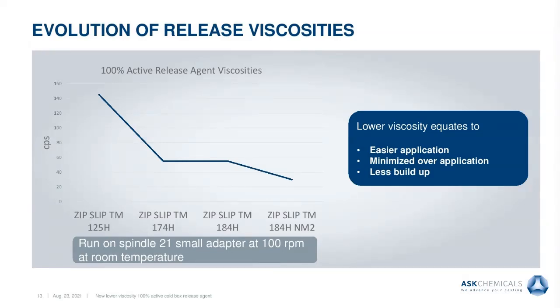100% active release agents have existed in the foundry market for decades. Viscosity is checked using a Brookfield viscometer run on spindle 21 at 100 revolutions per minute at room temperature. Originally, as developed, 100% active release agent viscosities started at the higher end of the viscosity spectrum, around 145 centipoise. Over time, viscosities of formulations dropped to 55 centipoise and most recently 30 centipoise.